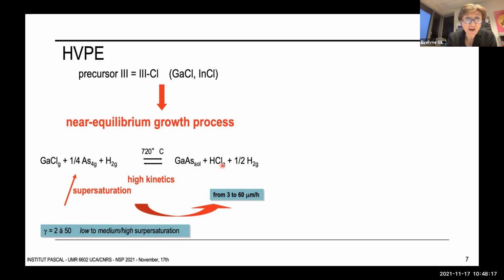So please note that the arsine gas, which is introduced in the hot wall reactor, is almost completely decomposed into As4, H2 molecules considered to be at equilibrium. And we will see later in this talk that when growing under undecomposed arsine, we can reach very fast growth regime. The dechlorination frequency is high enough so that there is no kinetic delay, and we observe an immediate return to equilibrium that produces the solid due to an increase of the supersaturation of the vapor phase.